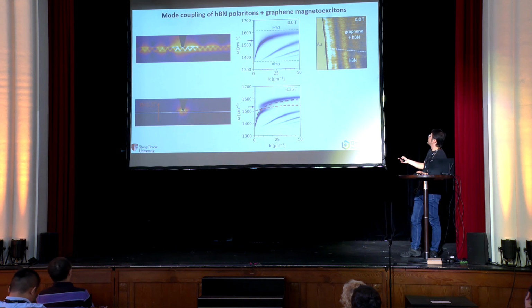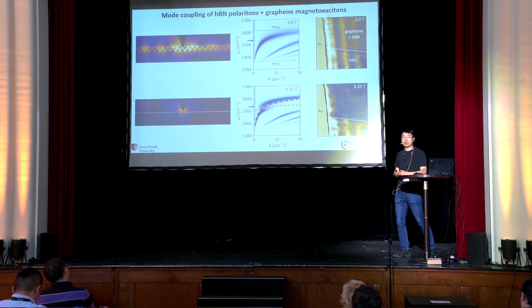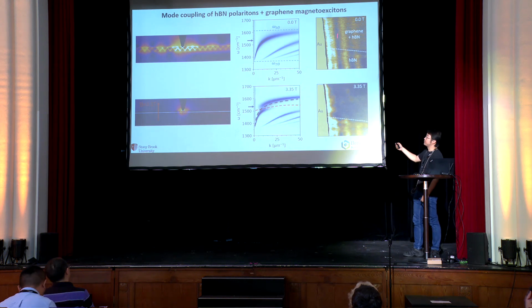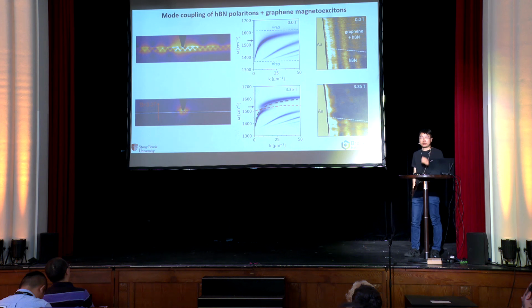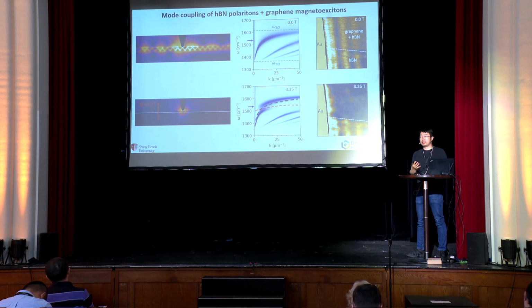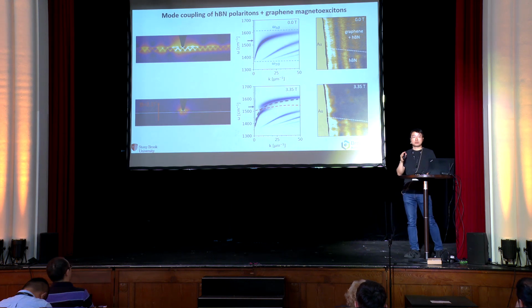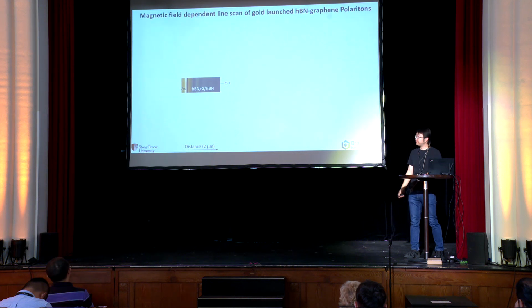And in high magnetic field, of course, since you have a gap opening, you will see that this polariton mode is totally stopped at 3.35 Tesla magnetic field. Okay? So this is a highly magnetic-field-tunable phonon polariton, or hybridized polaritons, that you can basically achieve at any frequency range, right? As long as you have phonon modes or other excitonic modes or magnon modes there, you can tune your Landau polaritons to match the frequency, which is nice.